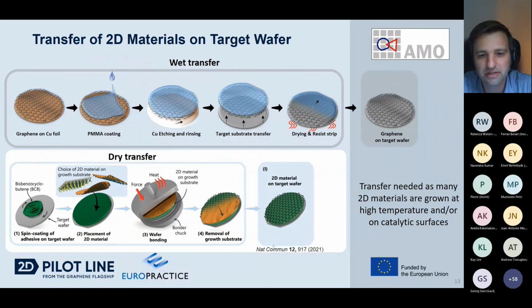And two methods I have displayed here on this slide. The first one, the so-called wet transfer, is called like this because it's mainly done in solution. You start here with your graphene, which is grown in this case on a copper foil. You coat it with a PMMA coating, and then you remove the substrate, the copper foil, by etching it in solution, and then afterwards rinsing it again. And so you end up with the PMMA layer and the graphene in a wet solution, which you then put on a target substrate wafer. And after drying and removing the resist, you end up with the graphene on the target wafer.